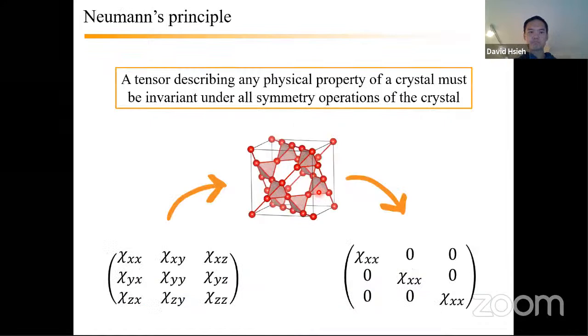As I mentioned, the fact that you're dealing with these higher rank tensors really encodes more degrees of freedom that give you sometimes more information about the symmetry properties of the crystal. Okay, so by Neumann's principle, we know that any tensor response that describes a physical property of a crystal, let's take this one for example, if you constrain that response to the symmetries of the crystal, then what you get on the output is some simpler tensor structure that embeds the symmetries of the crystal. So in principle, if you know these tensor structures, you can say something about the point group symmetries of the crystal.